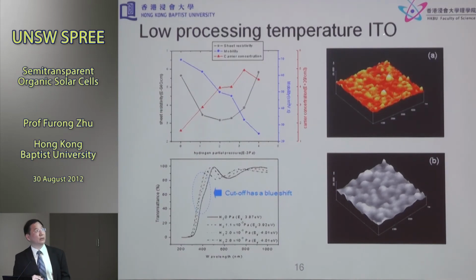If you remove too many oxygens, or the oxygen vacancy concentration is too high, then you have an over-reduced material, it turns black, and this is not what you want. So the black curve I show here is the sheet resistance as a function of the hydrogen partial pressure that you use. It's a very small amount of reducing gas.